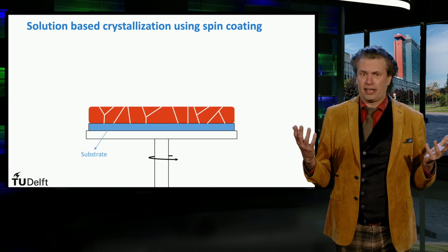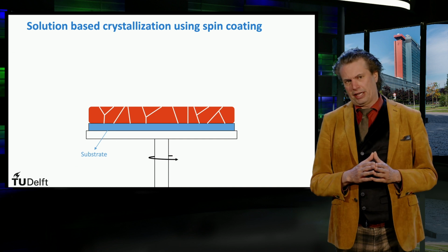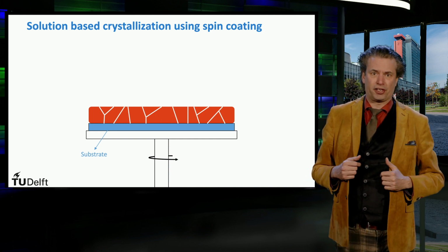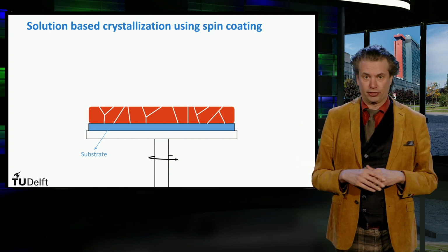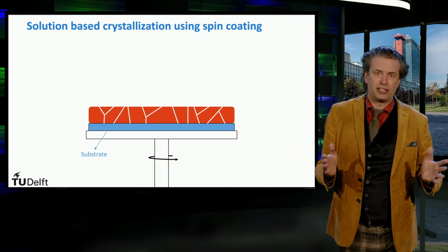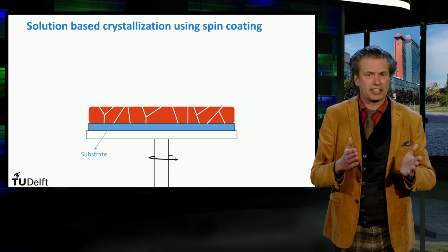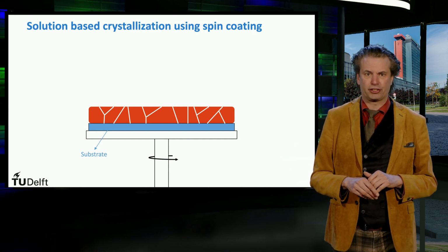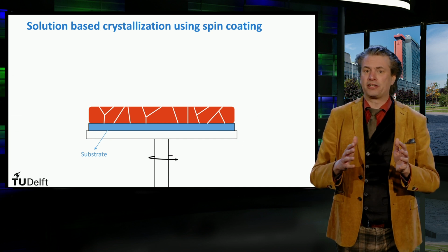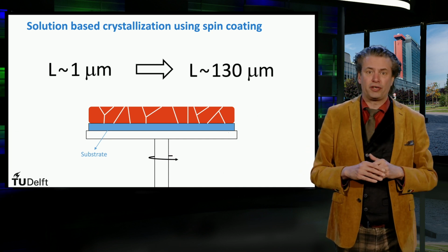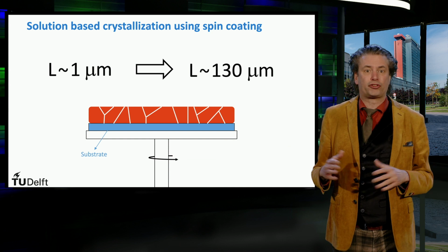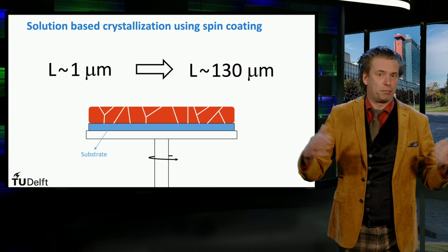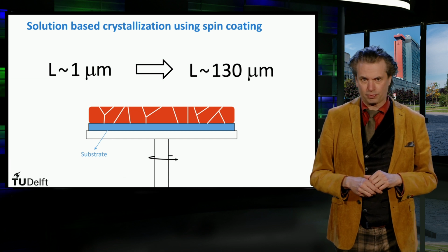The perovskite layer is a polycrystalline layer. This means that the layer consists of grains with different lattice orientations and grain boundaries. As grain boundaries are surface entities in the bulk that facilitate defects, they can enhance the recombination of light-excited charge carriers. By increasing the grain size or decreasing the amount of grain boundary surfaces, the diffusion length for charge carriers could be increased from 1 micrometer up to more than 100 micrometers.